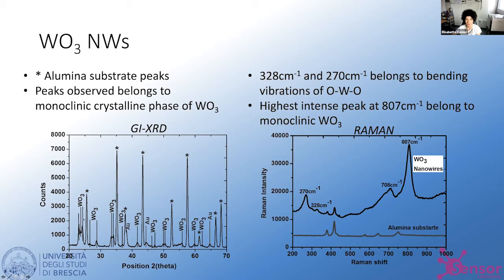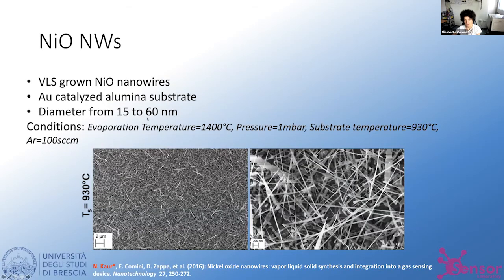And we have seen that we have a monocrystalline, monoclinic crystalline phase of tungsten oxide, which is confirmed also from the Raman spectrum. We have studied also P-type oxides, since it's really interesting to have different behavior, because N-type and P-type semiconductor metal oxides respond in a different way when the chemical compounds are introduced into the test chamber.